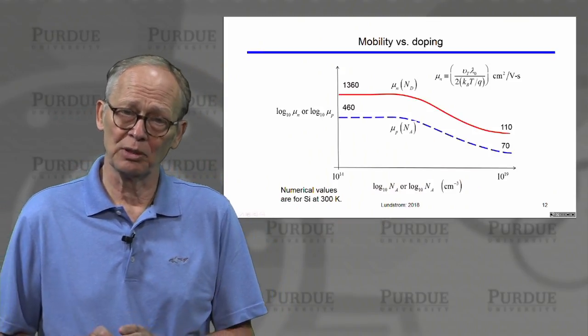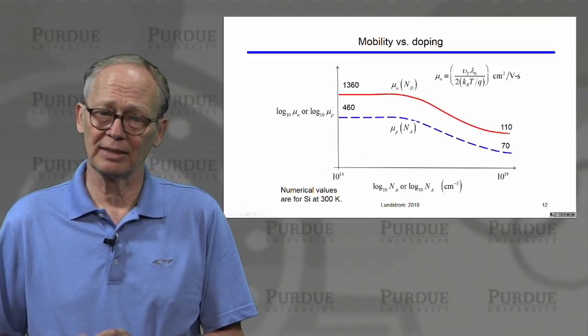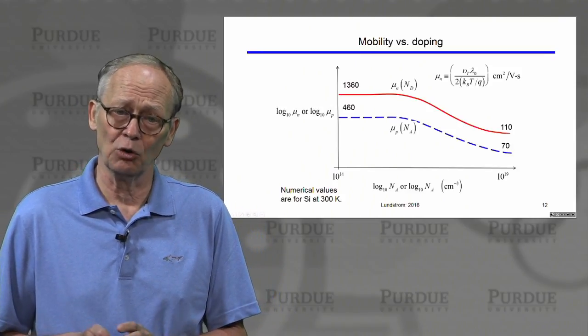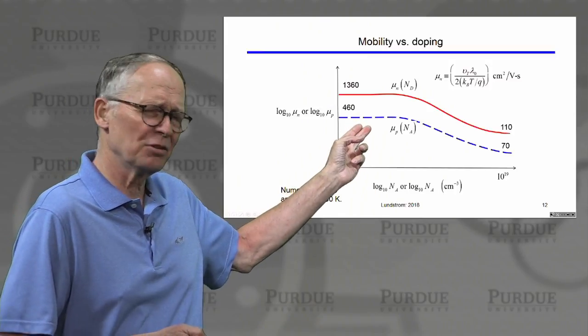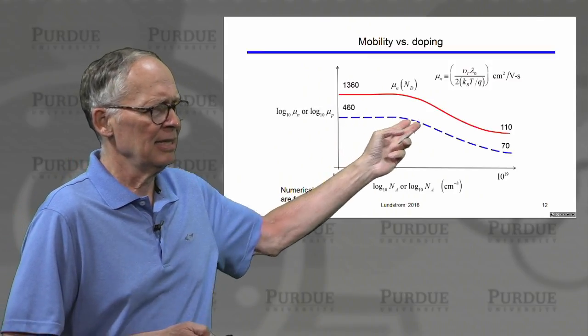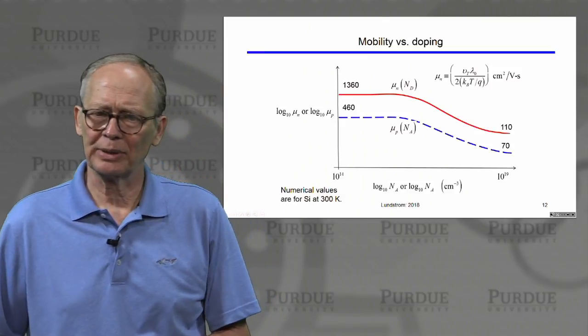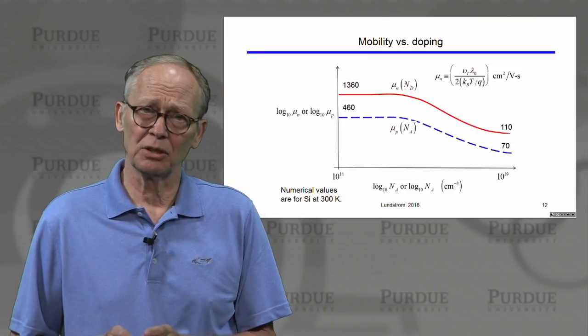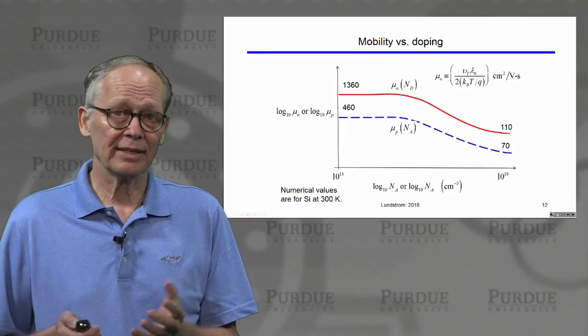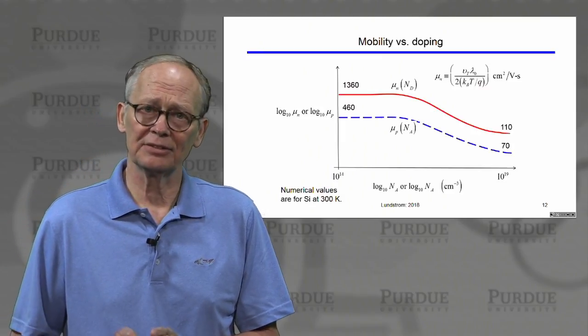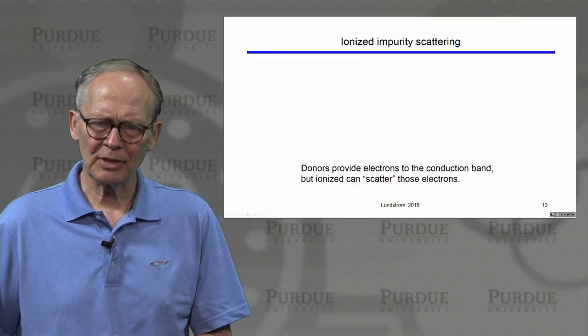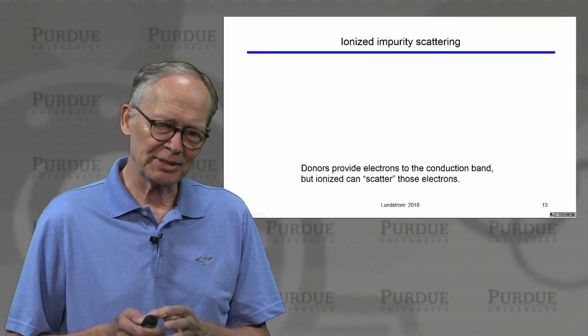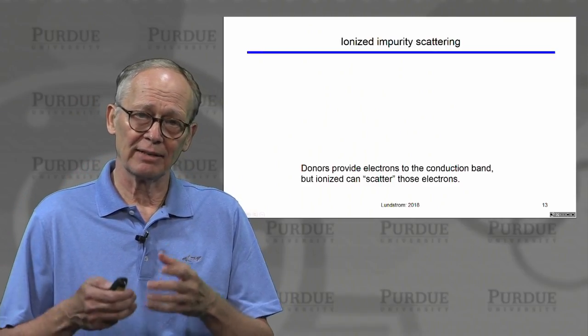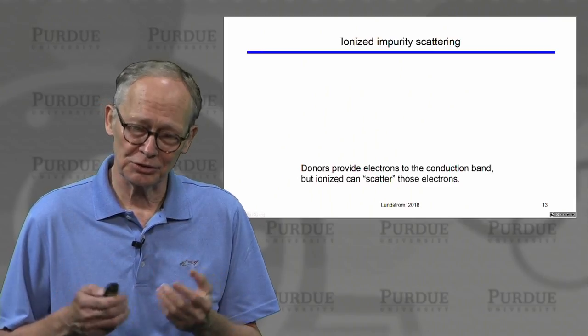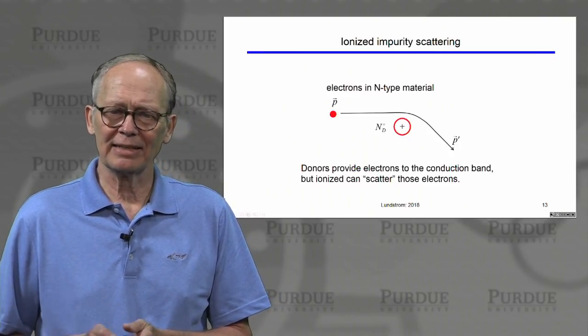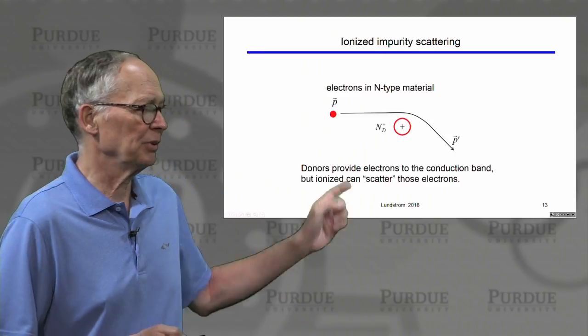I could measure the mobility for holes in p-type silicon as a function of doping. Hole mobilities tend to be smaller than electron mobilities, but as I go to higher and higher doping densities, the mobility gets lower and lower. Why is it getting lower and lower? Well, the reason has to do with increased scattering. So for example, in an n-type semiconductor, the donors provide electrons to the conduction band. That's what they're supposed to do. But they leave behind an ionized charge, which can interact with the electrons.